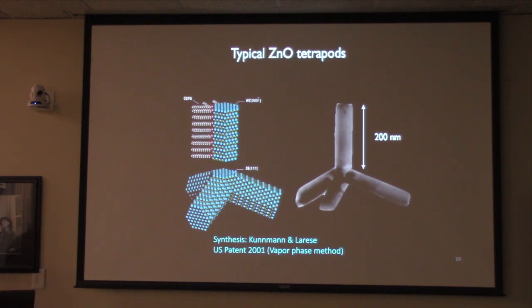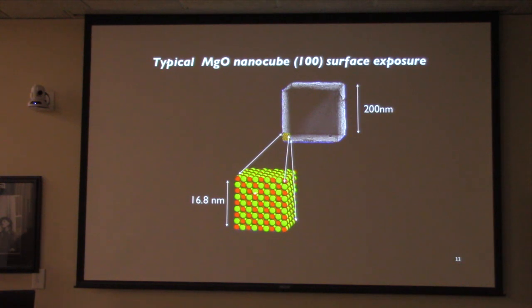So this is one of the classic materials that we've been looking at now, and the other one is how I first started, and that's with magnesium oxide. We can produce these cubes from 5 nanometers all the way up to 500 nanometers selectively, so they're a very narrow range. And in fact, some of you might know that if you talk about the stoichiometry, in our case is 1 magnesium atom to 1 oxygen atom, you can dope in things like metals, and then you can have the general expression Mg(1-x)R(x)O, and so we can put in things like copper or nickel or iron.